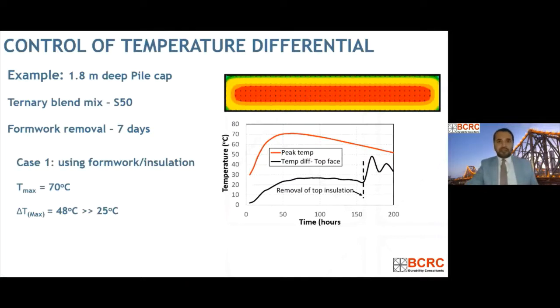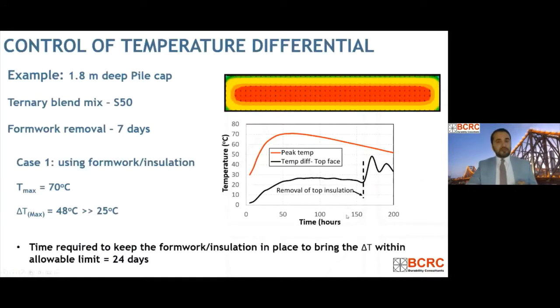Now to avoid that, because we're looking at the first case, we're using formwork and insulation to control this temperature. So we need to extend the period where the formwork or insulation are in place. We can extend that period and bring the temperature differential down within the allowable limit. In this particular case, we need to keep the formwork and insulation in place for 24 days. If you keep that in place for 24 days, you can get the temperature differential within the allowable limit, which is 25 degrees.